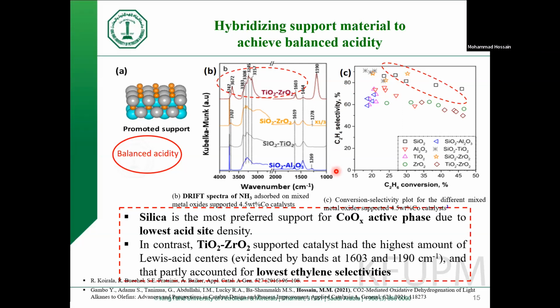Acidity is another important parameter that needs to be looked at. We need some acidity for conversion of hydrocarbon and carbon dioxide. However, too much acidity may create problems. So in this case, the acidity of the support or the catalyst has been adjusted by using different materials: silica, titanium, zirconia, and so on. Silica has been shown to be more preferred to disperse cobalt, in this case the active phase, and that gives the highest olefin selectivity, in this case ethylene. And for the others, the acidity was not favorable in terms of higher olefin selectivity.